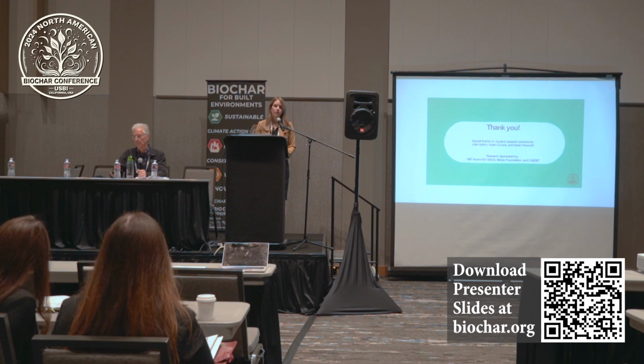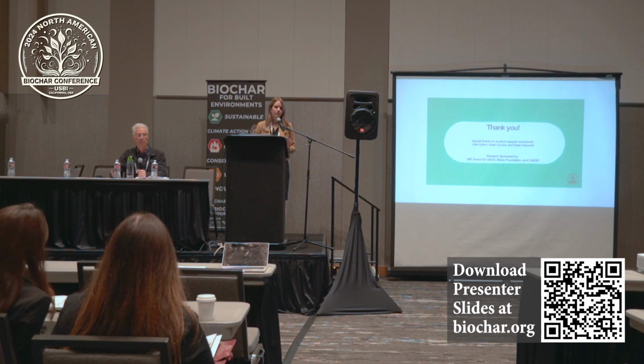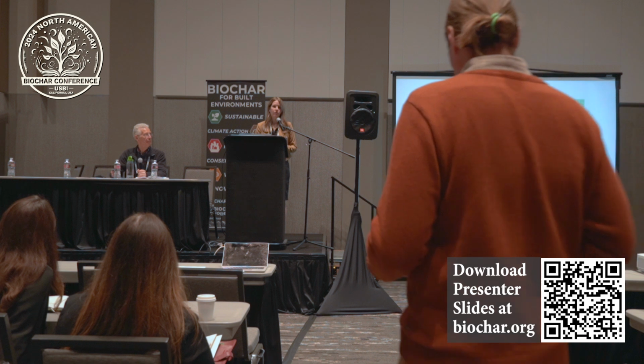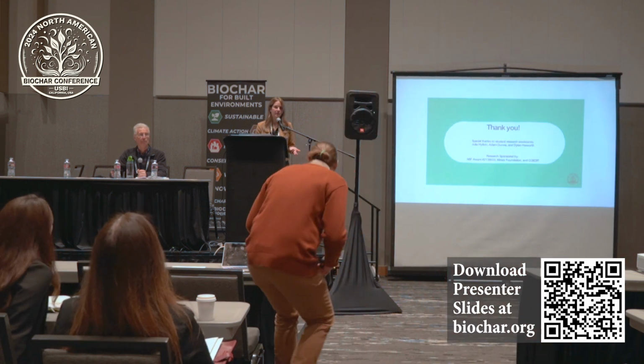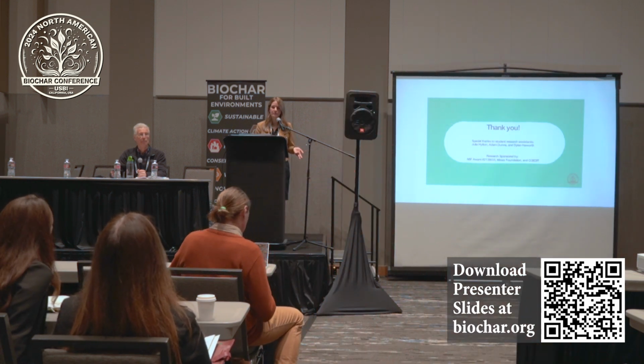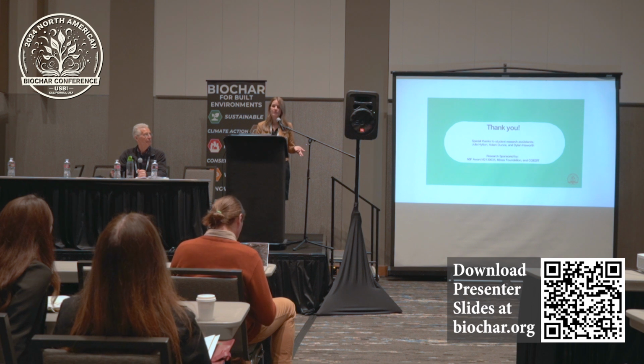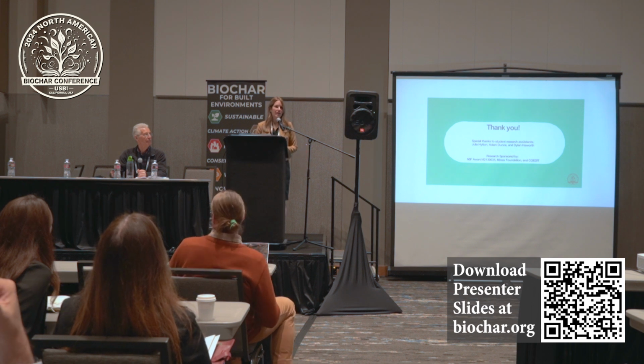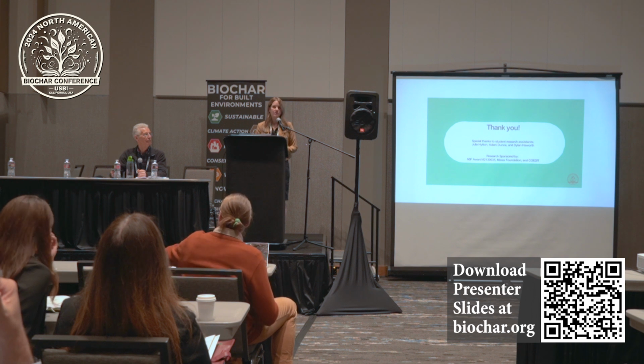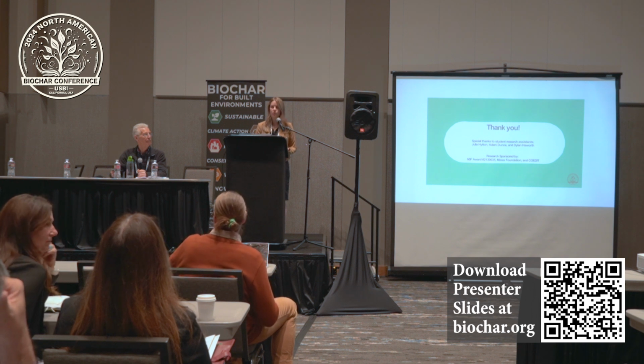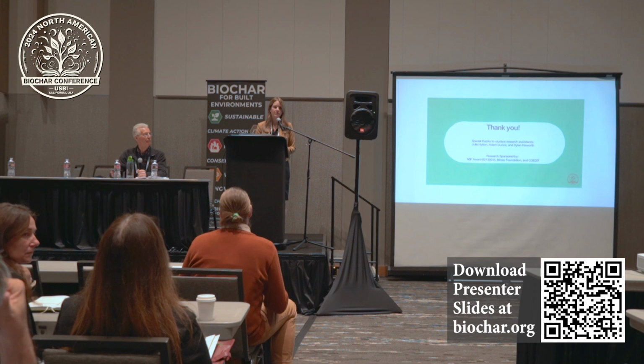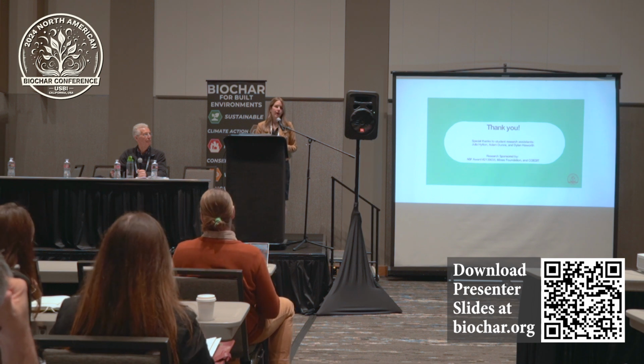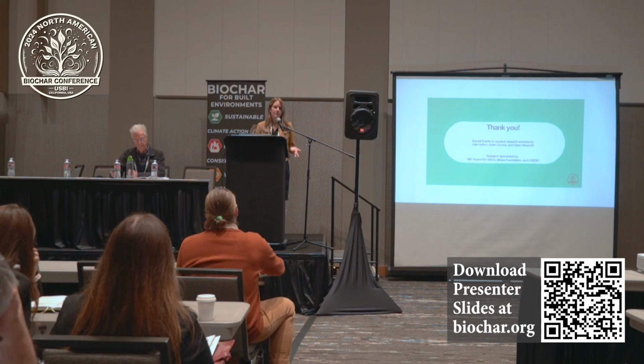Well, we haven't done a study on this systematically to purposely alter it to see how it's affected. We have found that it mills really easily. So all of the biochars we've tested, we mill for about 5 minutes, and it goes down to an average particle size of 10 microns within 5 minutes. So it's really not an aggressive milling operation. It doesn't seem to be time consuming or very energy consumptive. And we get to the 10 micron particle size pretty easily.